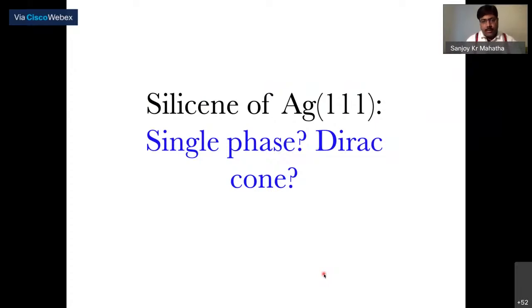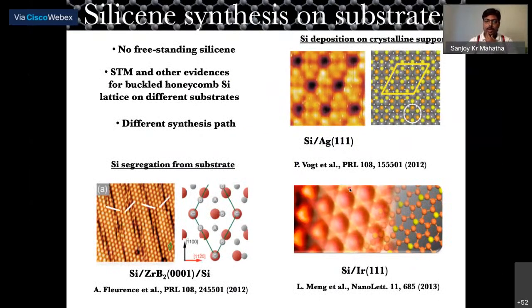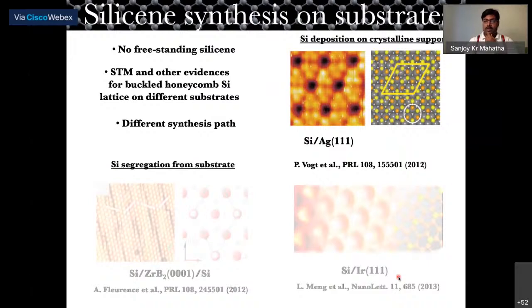So let's see if, for silicene on silver, we can achieve this single phase structure, and if so, do we see any kind of Dirac cone? Silicene was synthesized on different substrates, like silver 111, zirconium diboride, and iridium. But if you see the literature, most of the studies are on silver 111, and this has a special reason. If you compare the lattice parameters of silicon and silver, they are in a ratio of 4:3. That means if you grow silicon on top of silver, then every fourth atom of silicon would match with every third atom of silver. And that's why you would get this kind of structure.